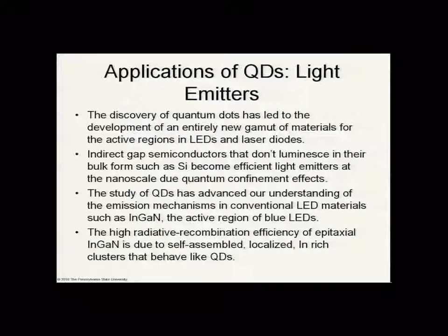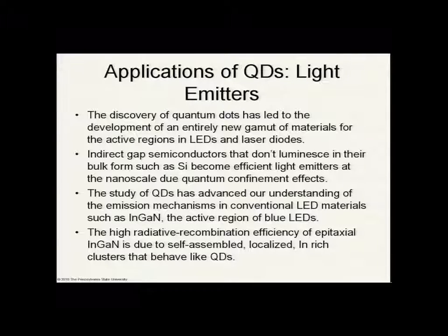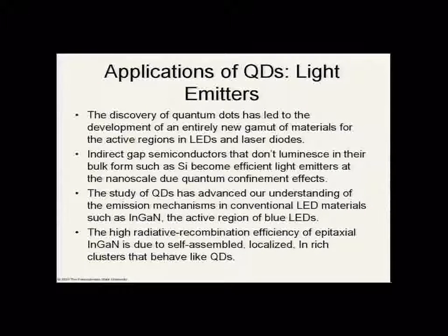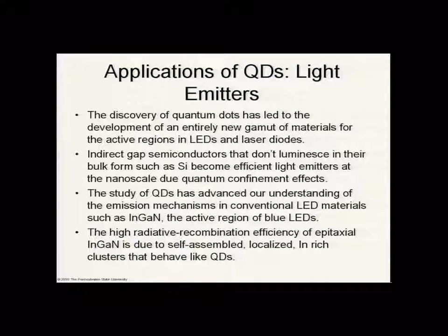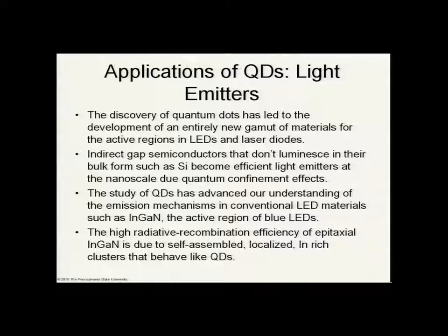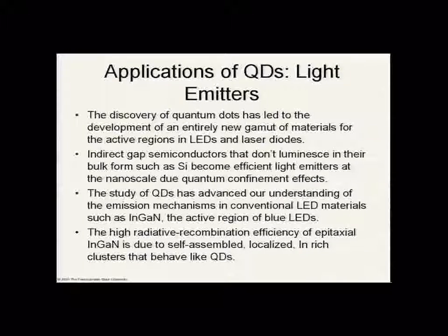The study of quantum dots has advanced our understanding of the emission mechanisms in conventional LED materials, such as indium gallium nitride, the active region of blue LEDs. The high radiative recombination efficiency of epitaxial indium gallium nitride is due to self-assembled, localized indium-rich clusters that behave like quantum dots.